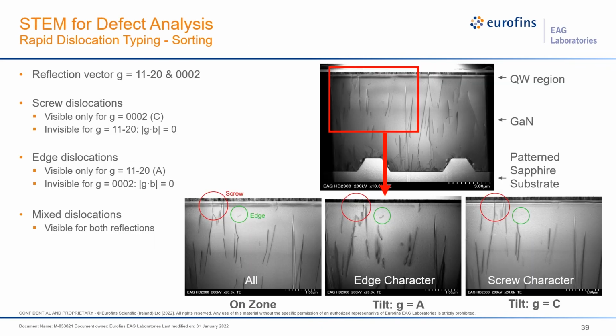But not only that, like I mentioned, we want to understand more about the type of dislocation that they are. So using some crystallography, we can then take 3 images, one on zone, and then one at different reflection vectors, one for the A direction, one for C. And in the case of the A direction, this gives us the edge character of the defects. And then in this reflection vector, this gives us the screw character. So then we can effectively tabulate all the different types of defects within the sample, within this cross section.